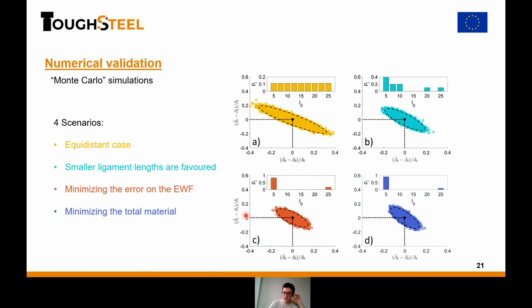But one thing you will realize is it doesn't feel great experimentally to just pick two bounds, because you don't really know what happens between them. So you need a way to still validate that you are inside this linear regime. What I did in my experiments is that I still had more samples with lower ligament lengths, but I was a bit more conservative, where I have a bit of a spread close to the lower bound and as well close to the upper bound. In this way, you still reduce a lot, compared to the equidistant case, the spread of the potential error that you make on the essential work of fracture.